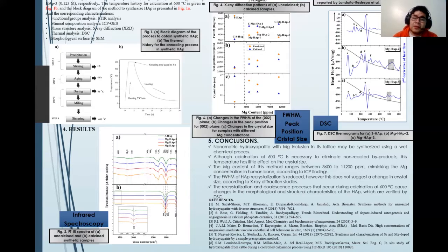At last, differential scanning calorimetry, the study of the thermal events during the calcination. Figure 7 shows the differential scanning calorimetry thermograms and their second derivative for samples from room temperature to 615 Celsius degrees. The arrows show the endothermic and exothermic events that take place because of the heating process.